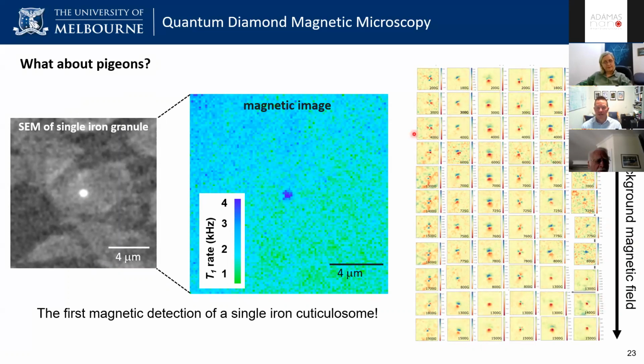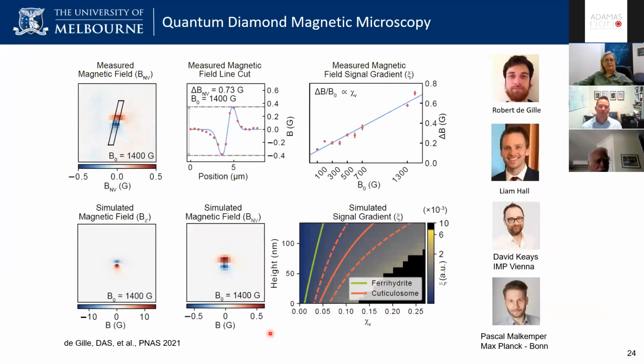And so using this data and the data that we collected from T1, we're able to understand more about the magnetic properties of these particular iron cuticulosomes. And so here are some of the measured magnetic images that we see. We see that the magnetization or the stray magnetic field grows with increasing background magnetic field. And working with Liam Hall and Rob DeGill, who was the PhD student leading this work, we were able to then simulate this scenario and simulate the magnetization these particles would need to have to match the measured images that we see.